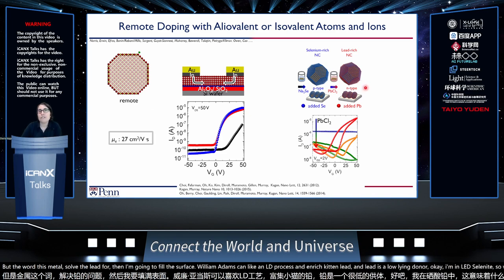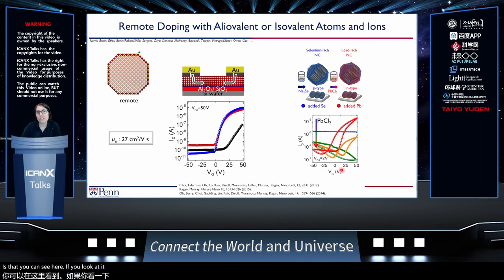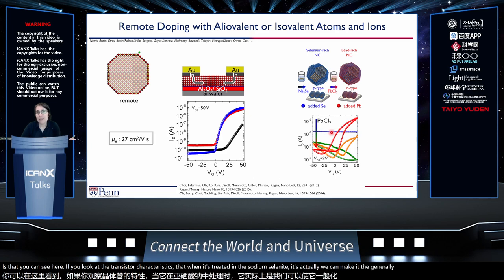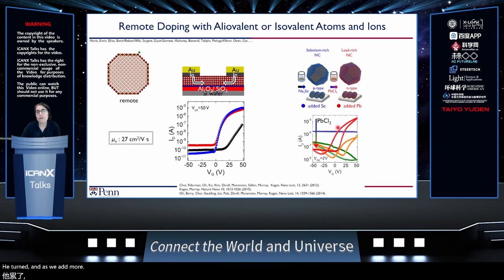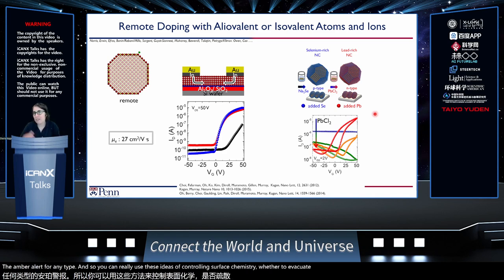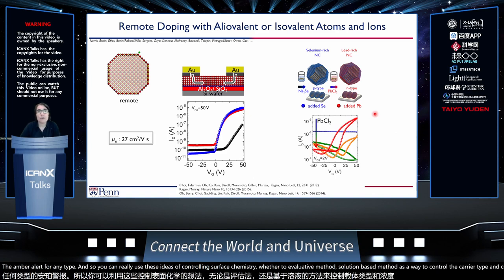As you can see here, if you look at the transistor characteristics, when it's treated with sodium selenide, we can make it degenerately p-type. And as we add more and more lead, it becomes less p-type, to ambipolar, to n-type. And so you can really use these ideas of controlling surface chemistry, whether through evaporative methods or solution-based methods, as a way to control the carrier type and concentration in these thin films of nanocrystal materials.